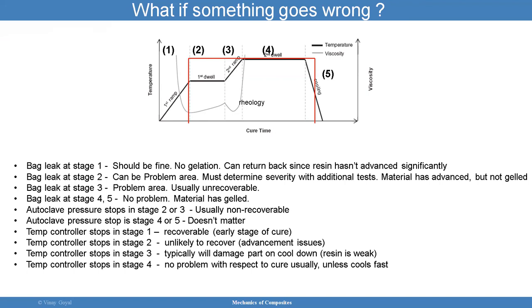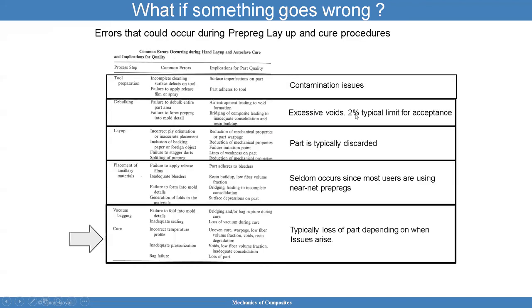And stage four, no problem with respect to cure, unless it cools too fast. If it cools too fast, you can have an issue. If it cools too slow, it shouldn't be a problem. But bottom line is there are a number of issues that could go wrong in the manufacturing of composites. And I was describing today the things that can go wrong. Here are errors that could occur during prepreg layup and cure procedures.